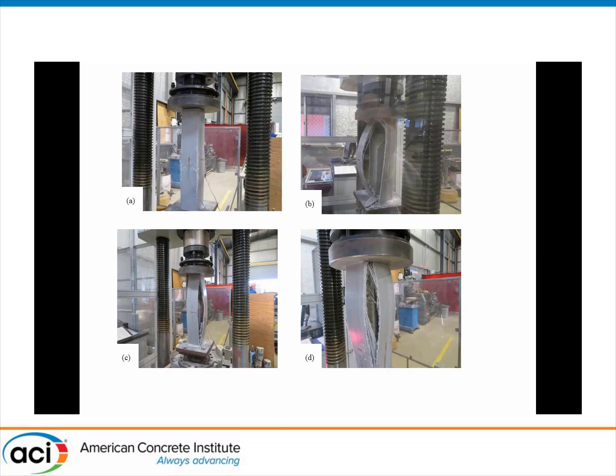This is about, I think, the 100 millimeter, 4 inch section, so about 5 times that height. The failure is that you start to get cracks on the sides when there is no pull winding or additional confining fibers. That's the type of failure we get, and inside, the concrete part is almost fully intact. And when you have the fibers, you get a different failure mode where this part is still intact, but you start to get a failure at the top. So these are some of the behaviors we are observing on the failures.